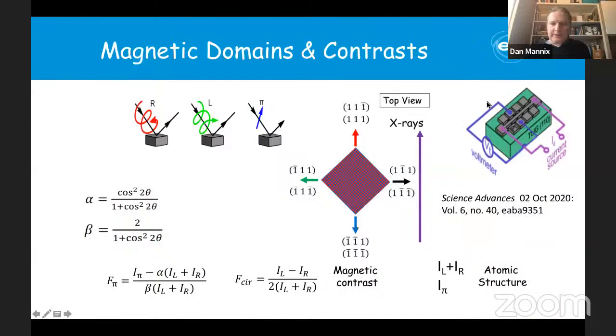So what have we done? If we go back to our sample now, and what we've been trying to do, we align our sample in a particular way inside our X-ray beam. We align the 110 direction parallel to the X-ray beam, so that we'll have one of these types of domains aligned parallel to the beam, the other one anti-parallel, and the ones perpendicular to the beam. As I was saying before, we would anticipate a very high contrast for these domains using circular light, and a higher contrast for these kind of domains using the pi light. And we can study the same Bragg peak and essentially get this kind of information.